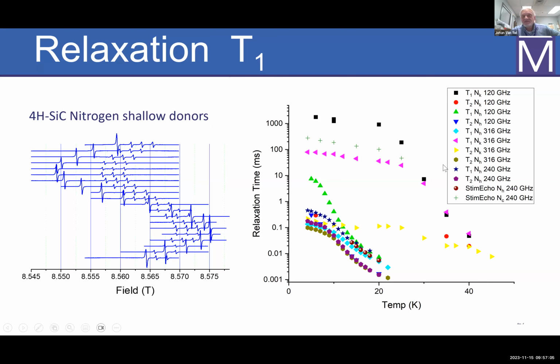But if you're looking at, and this is a very busy graph, I have to move a little bit for the light. So if you're looking just at the T1s in this case, at 120 gigahertz, the T1 is about 2 seconds, actually, at low temperatures. Now, if you go to 316 gigahertz, these purple ones, it's about a factor of 30 faster, so we're less than 100 milliseconds in this case. So that really corresponds to a frequency dependence of the frequency to the power 4.